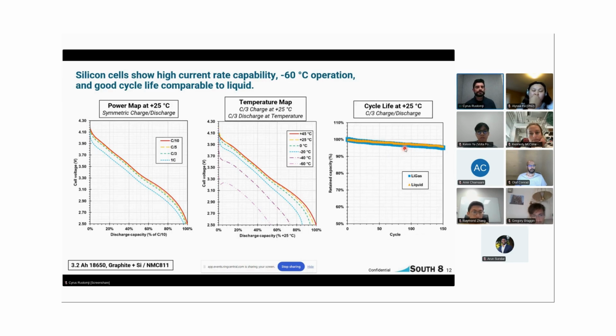Moving on to silicon. This is some work we've been doing with a partner. These are 3.2 amp hour cells, 18650 cell form factors with silicon in the graphite matrix and an NMC cathode. So power mapping this up to 1C is no problem for us. We can do power all day long. That's not an issue. Temperature map, everything from 45 degrees to minus 60. Again, looks great with these silicon anodes.